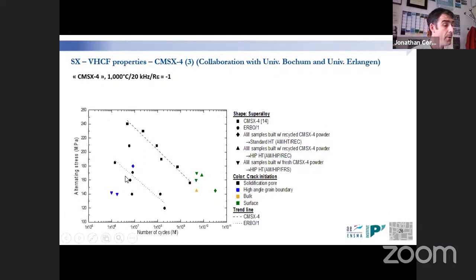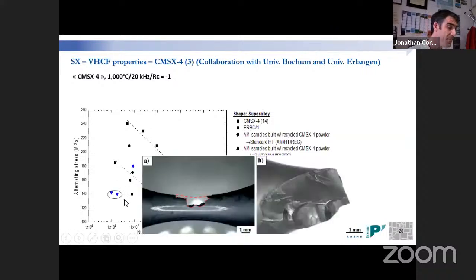Here we have a database of CMSX-4 processed by casting with large casting pores, meaning very large casting pores. And a database of CMSX-4 processed by casting with small casting pores. In all those cases, we have crack initiation at internal pores, the largest ones. Here you can see AM specimens which failed almost immediately because of the presence of high-angle grain boundaries.